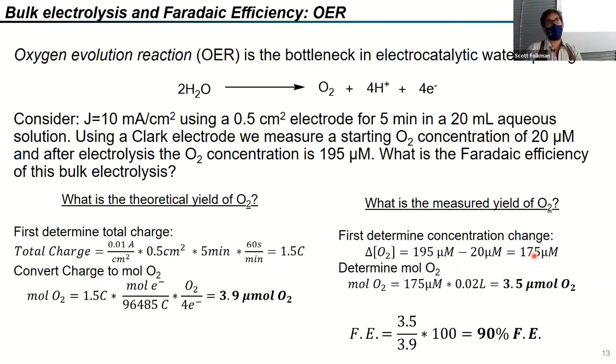You may not have that luxury. If that's the case, then you measure the oxygen in the headspace, and you can use Henry's law to determine what percentage of oxygen is still dissolved in solution, and do a summation of the oxygen in the headspace and the oxygen dissolved in the solution.